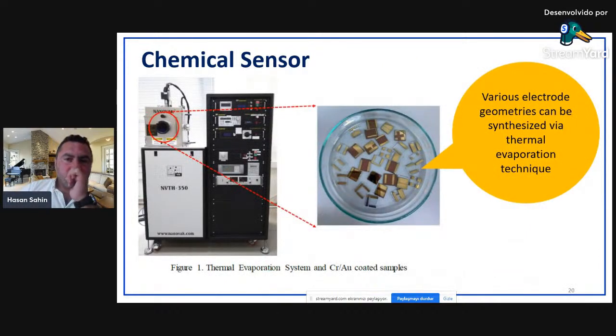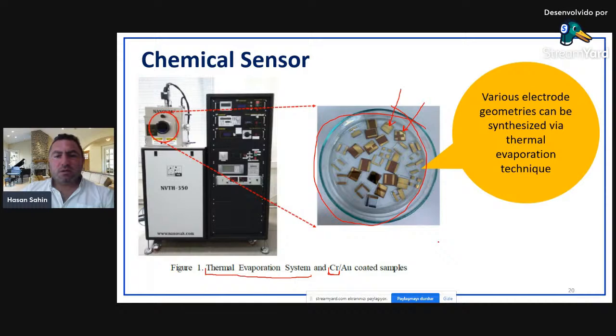And so how do we synthesize the electrodes and graphene? I'm not the one who is doing these things actually, but I know that they are using a thermal evaporation system, and our gold contacts, as you see here, are on a substrate. In between there is chromium, and this chromium layer provides a stickier behavior between the substrate and the gold electrode. So our electrodes are like this.